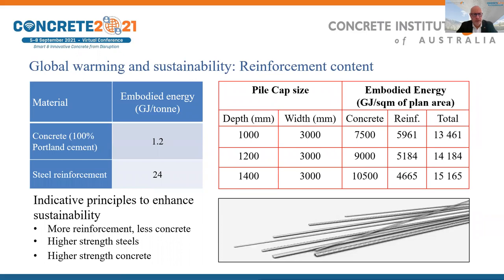While we're talking about sustainability, it's worth thinking about steel, because concrete invariably is married to steel as reinforced concrete. And looking at the embodied energy of steel, approximately 20 times that of concrete. The tendency is to consider that for a given reinforced concrete member, let's say in bending, it may be better to provide more concrete, increase the depth, and provide less steel reinforcement, steel being the higher embodied energy. Now, we've done some studies at Aurecon, and indications are, in fact, the reverse is true, that embodied energy is, in fact, let's say, optimized by providing more steel reinforcement and less concrete.